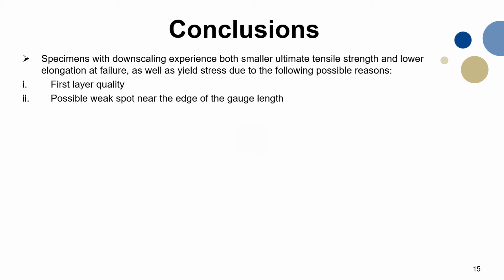And second is the possible weak spot near the edge of the gauge length, as I showed earlier. If we assume that for every scale we have the same defects, then relatively for larger scales we tend to have a lower percentage of defects and voids. That's why the elongation gets higher, as well as the ultimate tensile strength, when the scale is getting larger.